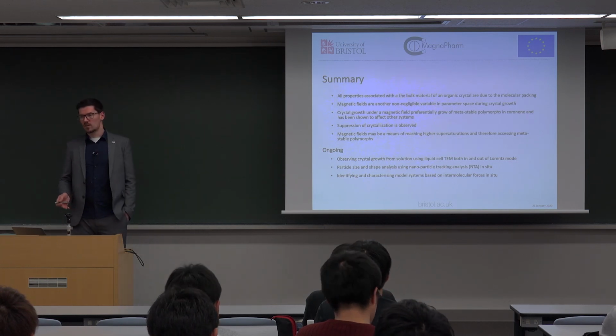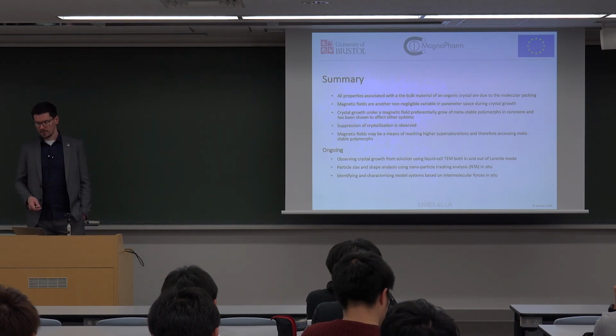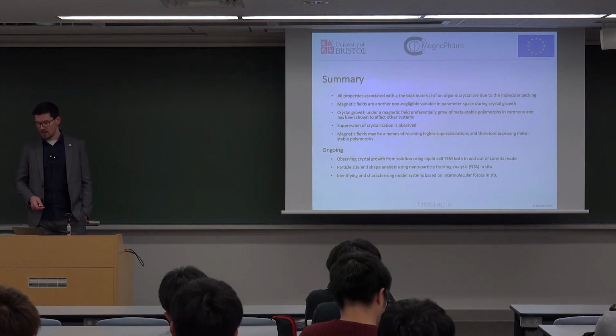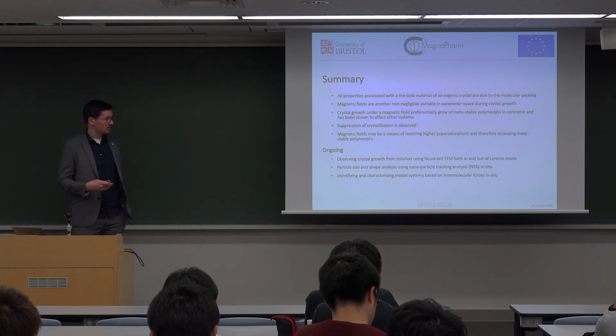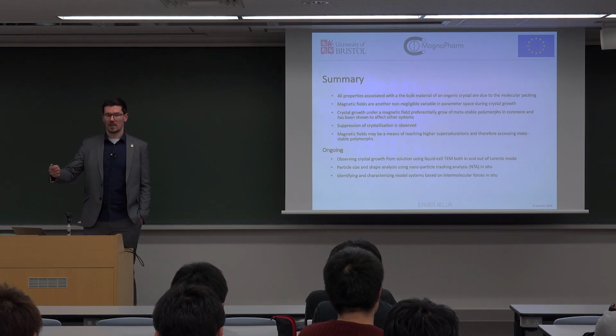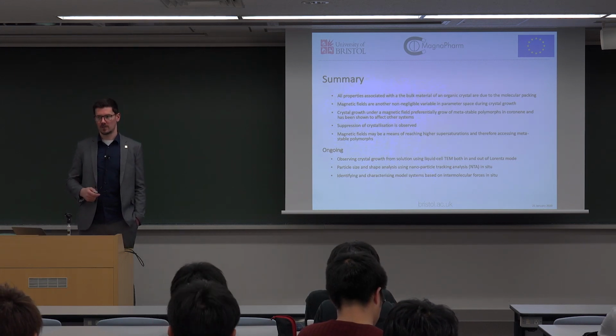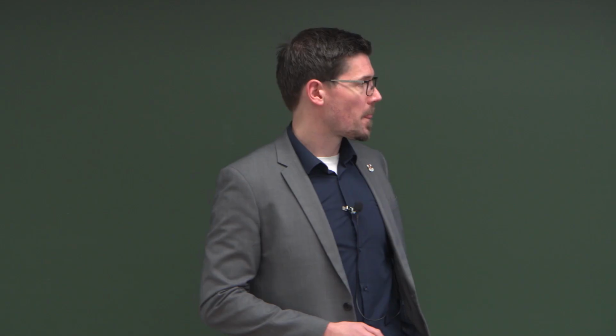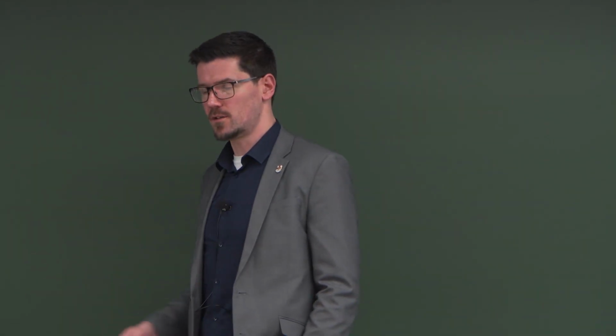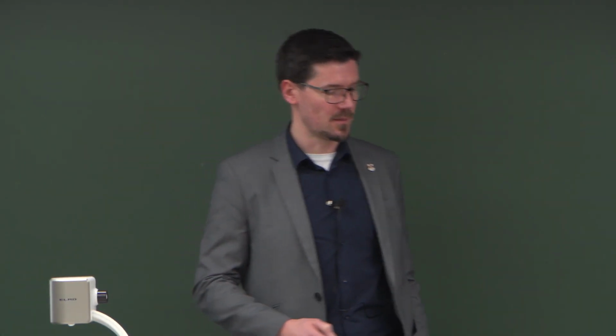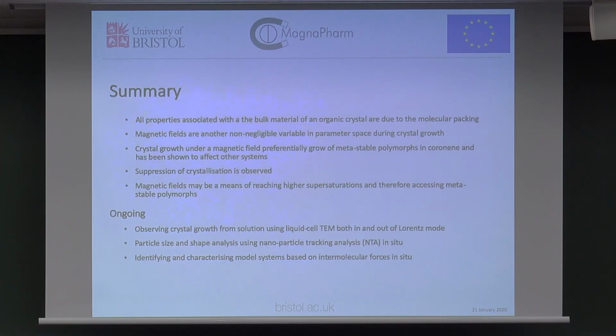It seems that there's preferential growth of the metastable polymorphs under field, and suppression of crystallization being observed. Looks like we're getting these metastable forms because we're pushing the supersaturation that far, and that magnetic fields might be a means of reaching these supersaturations that have yet been unattainable by other means. Just things that we're looking into at the moment. We've got a liquid cell over at Limerick, a liquid cell sample holder for a transmission electron microscope, which is very exciting. So we can watch these crystals growing.